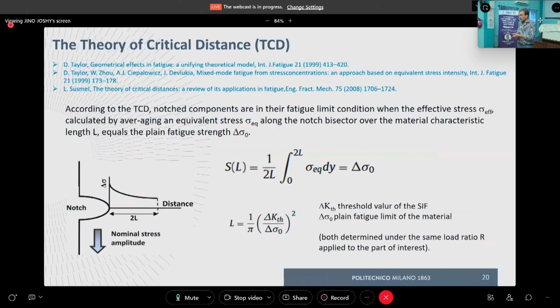And this is the formula. According to the theory of critical distance, the effect on the fatigue limit of the notched component can be determined when we calculate this equivalent stress, which comes from the integral of the trend of the equivalent stress along y, from the surface to the critical distance L. So S_L, that is equal to delta sigma, is the average of the trend of the equivalent sigma over this critical distance from the surface.